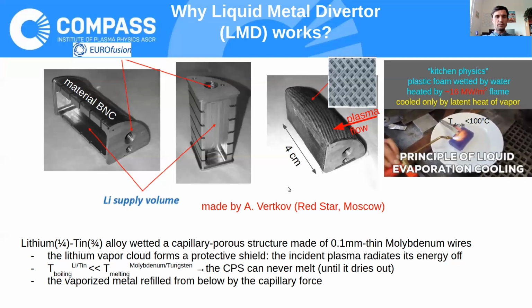Of course, in tokamaks we use other materials. We have used boron nitride carbide for the bulk, just wound with a mesh made from 0.1 millimeter thin molybdenum wires. This is what we call a capillary porous structure, and then it's wetted by lithium tin alloy in our case, or it can be pure tin or pure lithium. And the lithium also then forms a cloud of vapor, which is a kind of protective shield, which radiates the energy of the incident plasma out.